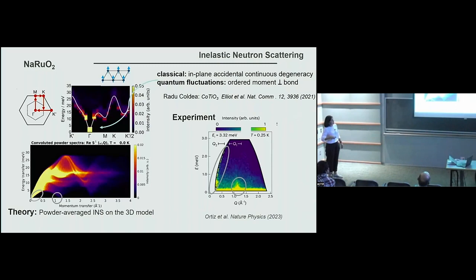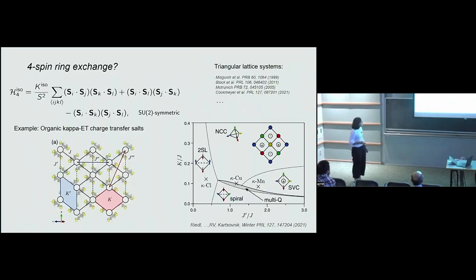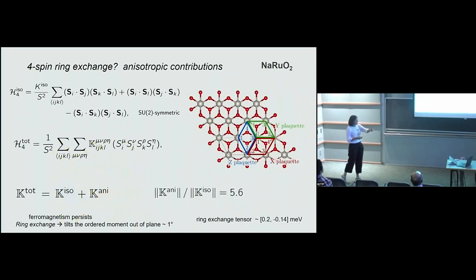intensity observed in experiment, and in fact this at Q equal 1, which comes from the stacking in the 3 dimensions. The 4-spin ring exchange, how important is it in this material? It has been observed that it's very important in triangular lattice systems. And here it's shown, for instance, in the kappa ET, you can explain many of their orderings by assuming this ring exchange. And this is my last slide.